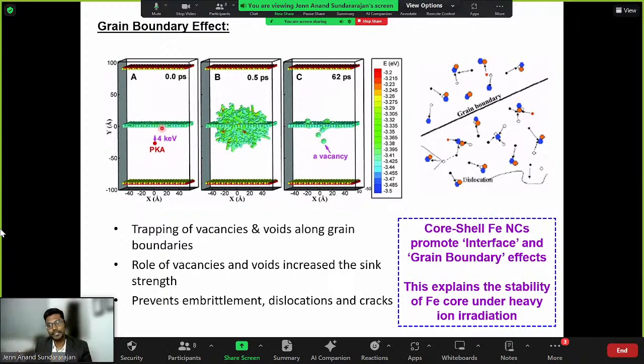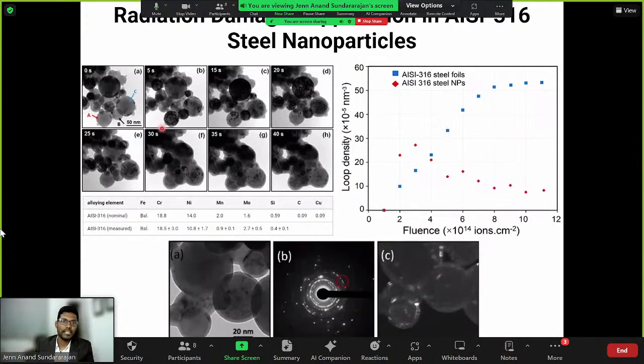And what do core-shell nanoparticles do? Because they have a core, a shell, and an interface, as well as multiple grain boundaries too. Here is a study I want to show. It's a very recent study from 2020, and it shows how the particles behave under irradiation. As you can see, these particles have a core and a shell. That's a surface, and these are polycrystalline. From the study, you can see multiple lines, so it's polycrystalline. You can also see that these particles have some pre-existing voids in the interface, and that could act as a sink to help dissipate the voids created under irradiation.